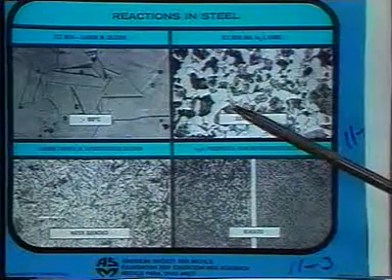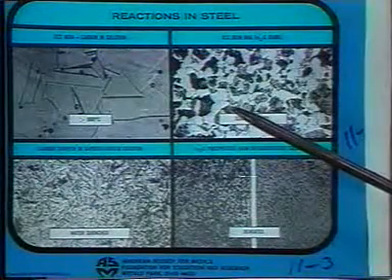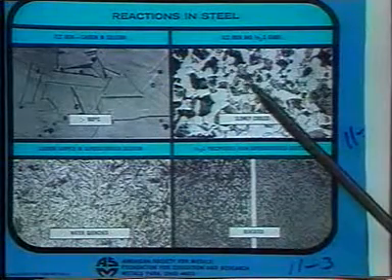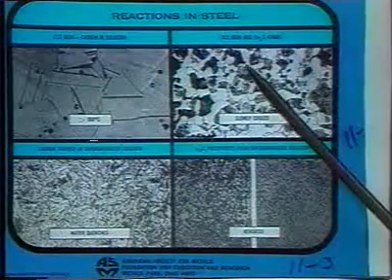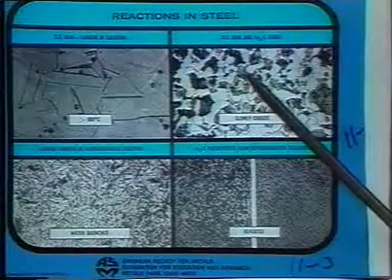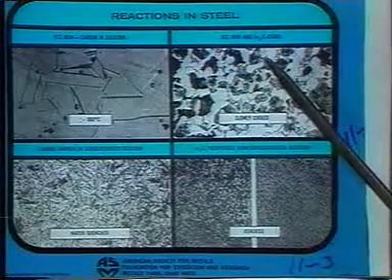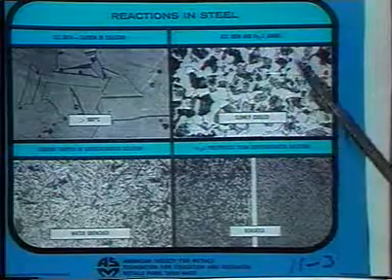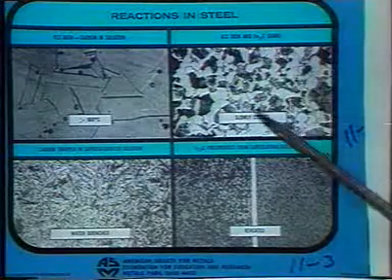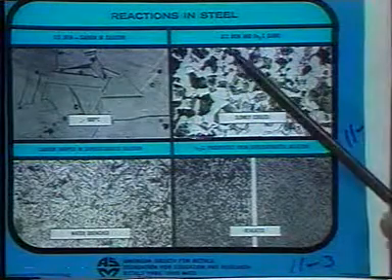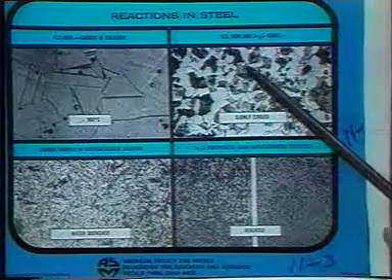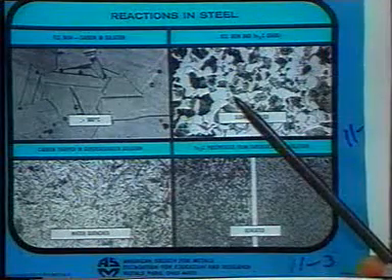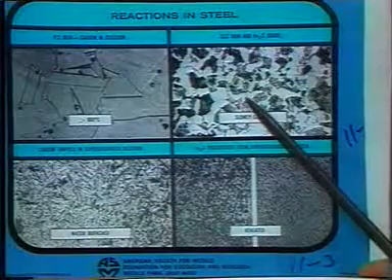And when somebody says, oh, this is a completely pearlitic structure, what they mean is that the structure all consists of what looks like a black island here. What that black island is, is a layer of ferrite and a layer of cementite, and a layer of ferrite and a layer of cementite. But it says that all of the carbon that's in this piece of steel resides in these little dark pockets. But even within the dark pockets, it's distributed into layers of iron carbide and iron and iron carbide and iron.